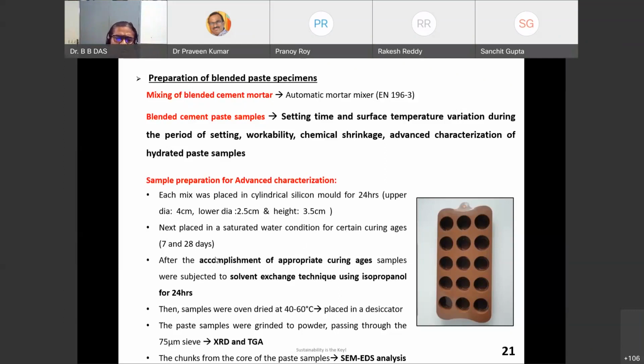Once they attained a certain duration, for example 7 days or 28 days, their hydration was stopped through the solvent exchange technique using isopropyl. Because for advanced hydration studies, we are not going to get a slot on the 28th day or maybe the 56th day or the 7th day. So we have to stop hydration and keep the sample in a desiccator. Whenever we get a slot, we take the sample and go for advanced hydration studies like XRD, TGA, and also SEM with energy dispersive spectroscopy.